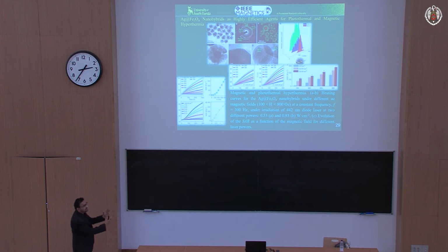So what we did here, one of the students came and we tried to combine and make hybrid nanoparticles. In this case, we can make these kinds of nano clusters by using silver. We can also do it with gold. Gold is even better to use as a seed, a metallic seed, and we can grow these clusters of magnetite, making these little nano flowers. Okay?